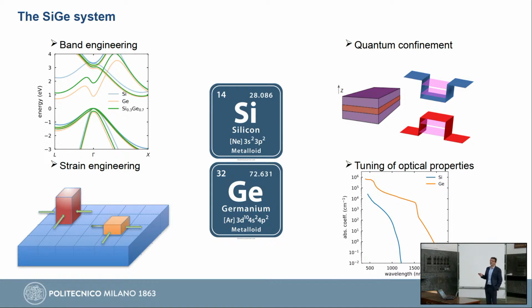They also have a different lattice parameter, which means that if I grow one on top of the other, I could impress some compressive or tensile strain on my system. And those of you who have already taken some solid-state physics know how important symmetry is in a crystal. And so here we are breaking symmetry, at least in one direction. So for example, we can remove degeneracy and engineer the electronic properties of our system.